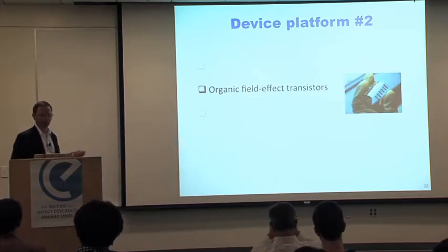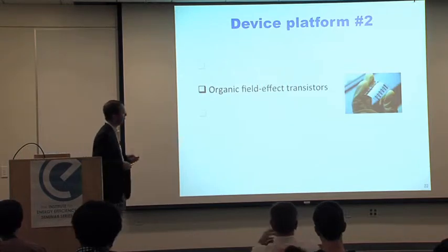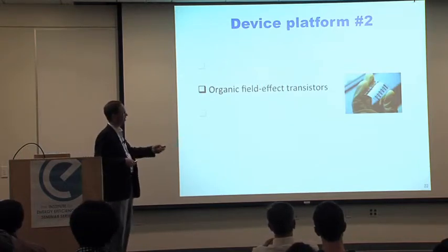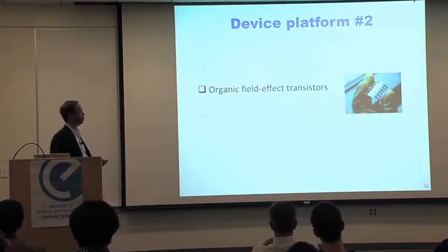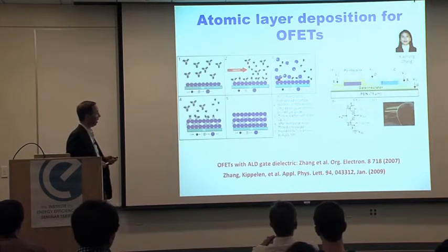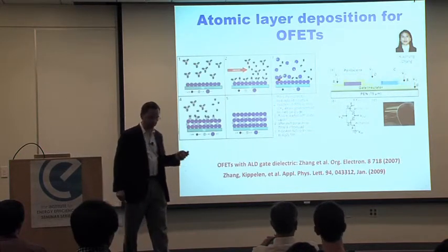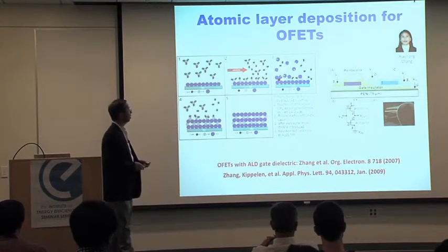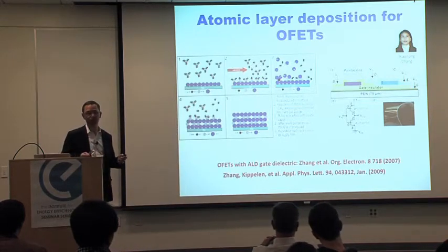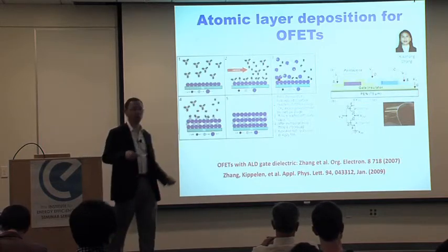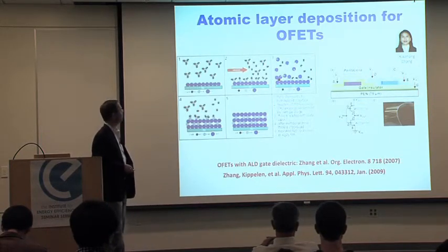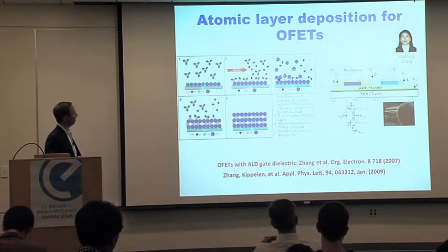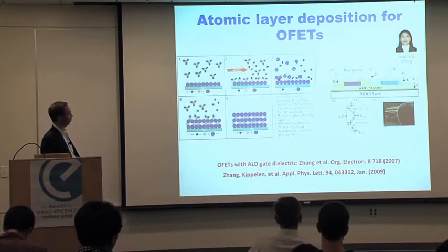And so some of the work I decided to talk about in this area today is not about making the transistor that has the highest mobility, but showing you that you can build device architectures that are very robust. And what's behind a device architecture with good stability is a process called atomic layer deposition, or ALD, which was developed for conventional CMOS technology, where you can make very high quality, dense and pinhole-free dielectric layers from the repetitive reaction of different precursors.